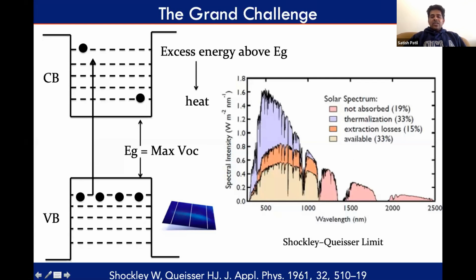I showed you the animation. Thermalization losses is 33%. You put a metal contact on a semiconductor, there are defects at those interfaces, those are extraction losses, and the total available limit for a band gap of 1.41 eV is 33%. So you are basically losing almost more than 65 to 70% of the light without doing any work here.